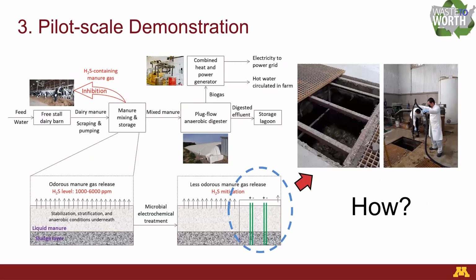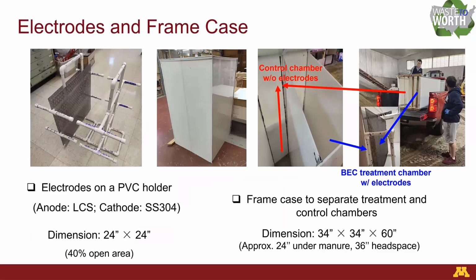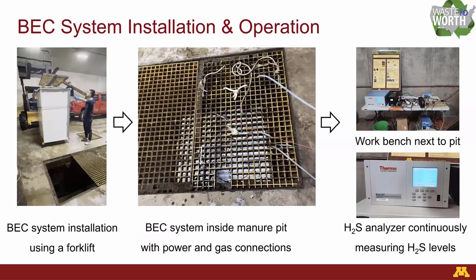So after that, we want to apply our technology into the real farm conditions. The question is how. So we designed and installed a larger scale one. Large pieces of low carbon steel anode and stainless steel cathode were mounted on a PVC holder, and a big box was built to separate the treatment chamber and the control chamber without the electrodes. Then we installed that in the manure pit, operated for over 2 months, and the hydrogen sulfide analyzer continuously measured the hydrogen sulfide levels from the 2 chambers, the treatment chamber, the control chamber, and also the ambient air as a background. So that's the result.